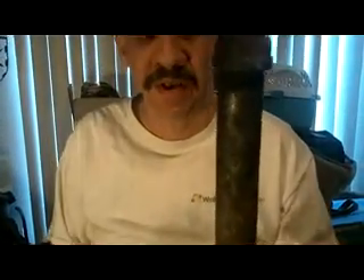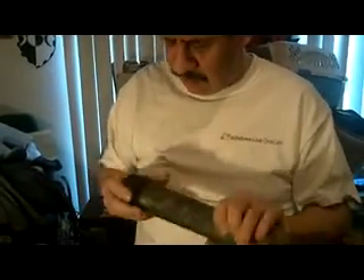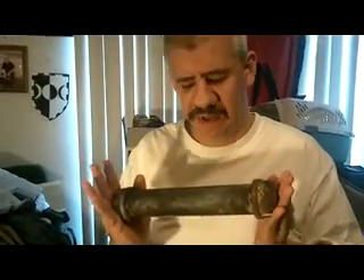I have found that a pipe such as this — this is a galvanized pipe — works really well. It seals really good and holds quite a bit of material to carbonize. When using a pipe like this, they are galvanized, and what you have to do when you first get it is burn it in fire and burn off all the galvanization. Because if you don't, you will get silver adulterated pigment, which looks really pretty until you grind it, then everything turns gray.